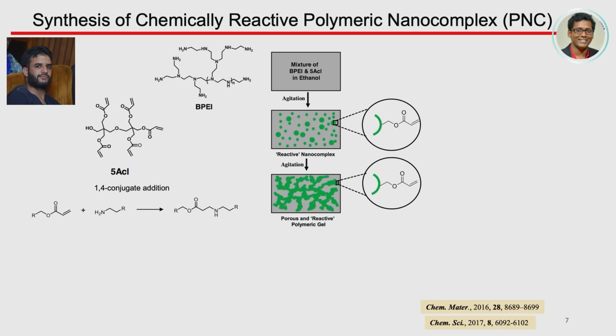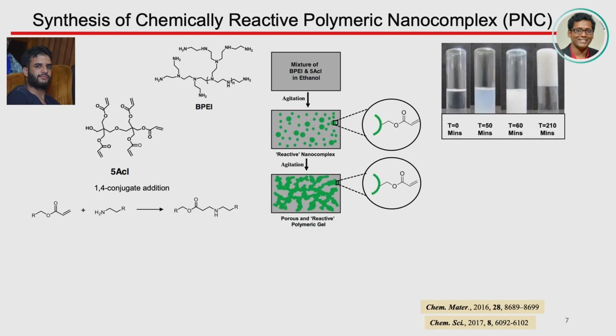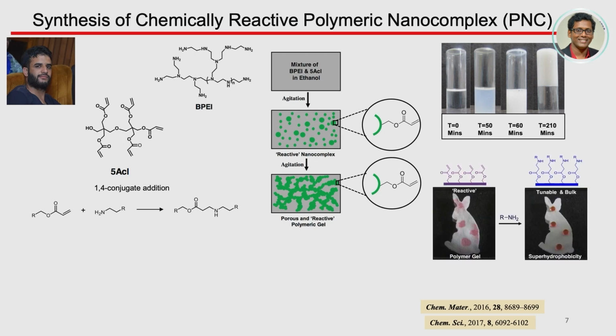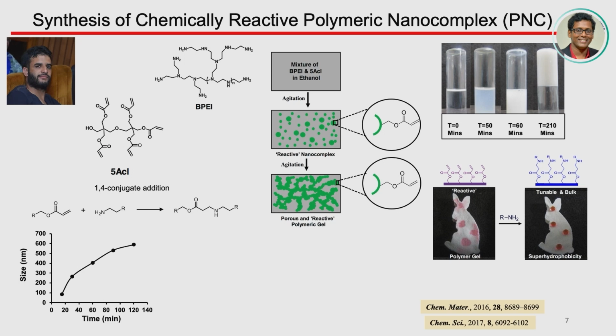Now, at a specific reaction composition of these two reactants, you will see the sol-gel conversion through this nanocomplex formation. As you can see, it started with a clear solution and it's forming a gel, and you can give it different kinds of shapes. As you can see here, we can give the shape of a bunny, and this bunny is initially hydrophilic. That's the reason you can see the red colored water is soaked. But after the post-modification, because it has a residual acrylate group, it can extremely repel the interface. Not only that, if you erode the top surface, the underneath surface is also capable of repelling the water droplet extremely. But our aim was not to prepare this kind of monolith and play with this bunny's wettability. More, we are interested in this reactive nanocomplex.